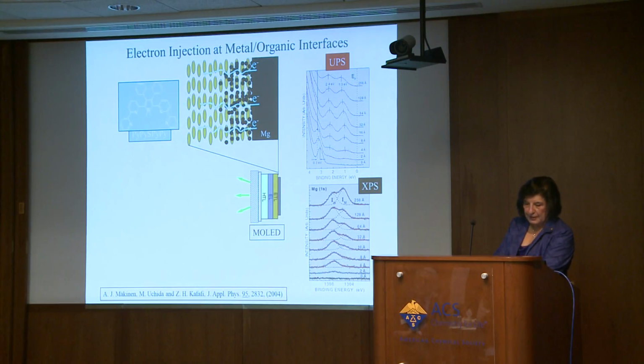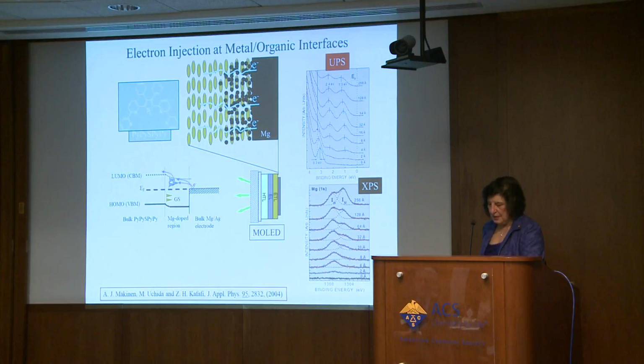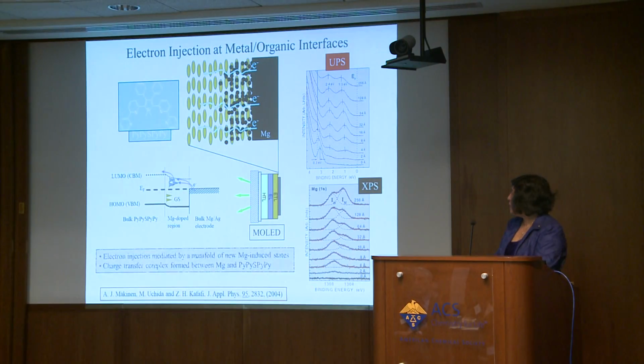silole derivative. And what we found is that magnesium, which is a low work function material for injecting electrons, has electron injection mediated by a manifold of new magnesium-induced states, and a charge transfer complex is formed. This was confirmed by XPS and UPS between the magnesium and the organic silole derivative. So there is this interface that mediates or facilitates electron injection and makes it more efficient.